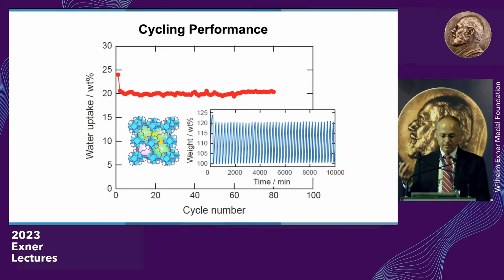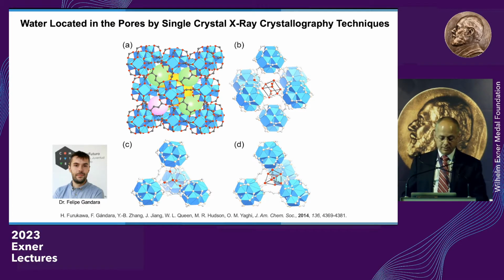And the nice thing about having worked very hard on the crystallinity of these materials is that now we can go in with X-ray crystallography and neutron diffraction and examine where the first water molecules are residing. And we find that they are in the pores and they're interacting with the metal oxide units. As you increase the amount of water in there, they can make tetrahedral shapes or cubic shapes. And it turns out these are the seeds that are bound tightly to the metal oxide unit, onto which other water molecules from the air will be bound. So this is why you have a cooperative phenomenon: these seeds invite other water molecules to bind and help in the filling up of the pores.